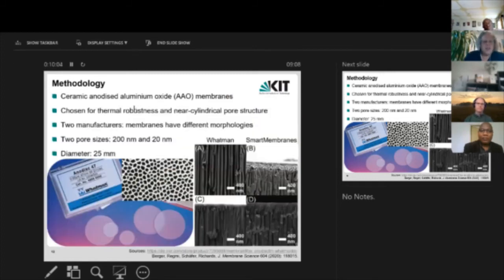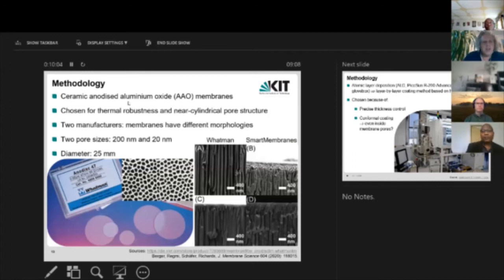So which membranes are we using? With this work, we initially started by using ceramic membranes. These are anodized aluminum oxide membranes. We chose these because they have good thermal robustness. This means that they will survive our later calcination process for the titanium dioxide. And they exhibit a near cylindrical pore structure.